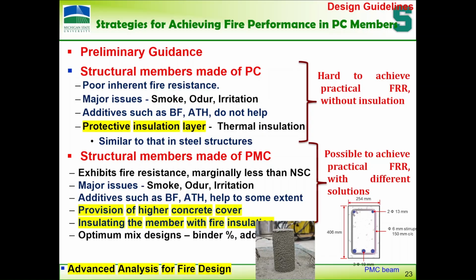You see here cylinders, at the cylinder level, because of the complications involved in high temperature testing. If you go to PMC, polymer modified concrete, you saw that it's good. So, all you need, we are proposing, not insulating. Insulation becomes expensive, but if you insulate it, go ahead with that. Otherwise, adjusting the cover thickness, maybe small dimensional changes is possible, that's one possibility. Second possibility, obviously putting the insulation, and even without both these, it may be possible if we play around with this, but still it's preliminary. So, this is what we are looking at, okay?